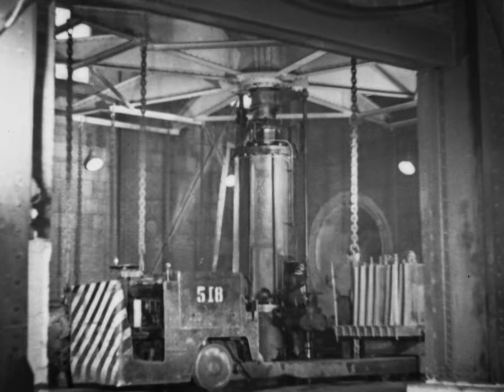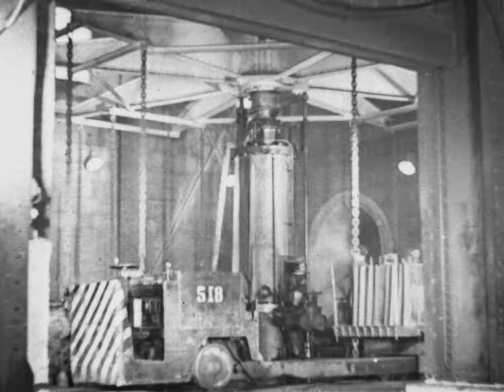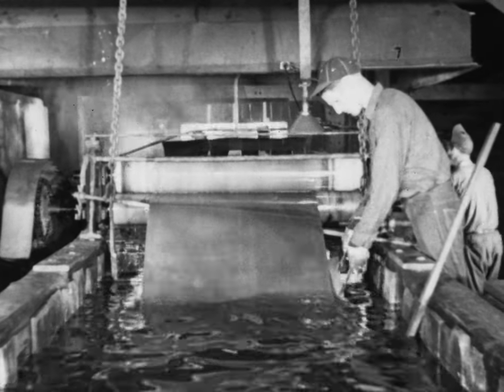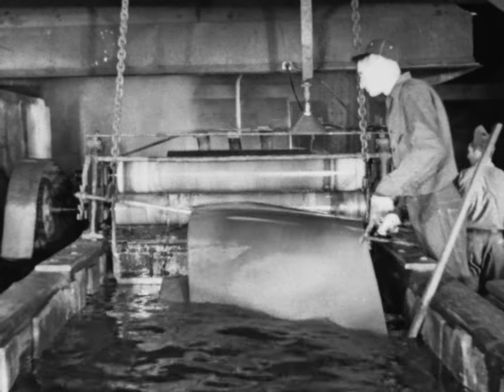For many uses, sheet metal is coated with zinc to give it longer life, and that's called galvanizing. First, the sheets are thoroughly cleaned. Then they pass slowly through a bath of molten zinc. A frost-like spangle forms as the zinc cools and crystallizes. Some galvanized products can be more easily and more economically made from coils, and these also come from ARMCO mills.